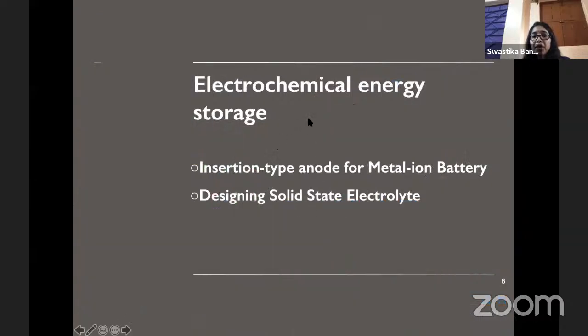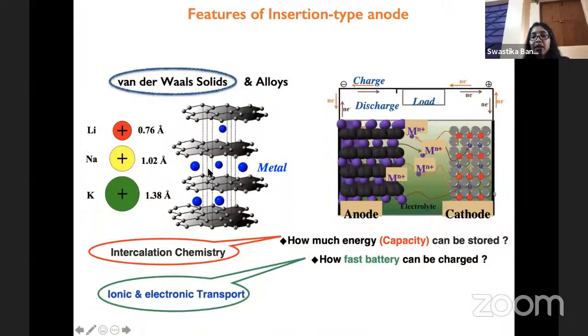However, for electrochemical energy storage, where we have problems with safety or energy density, we are going to deal with these two strategies. And the first one is the insertion type anode, as I was mentioning. So an insertion type anode is basically a van der Waals kind of material, and we can intercalate the respective metals. Like for lithium ion battery it is lithium, for sodium or potassium it's the respective elements. So we need to choose the layered system in such a way that it will allow the intercalation chemistry, which has very tricky criteria: how much energy can be stored depends on how many ions you can store, and how fast the battery can be charged depends on how fast these elements can be transported through the material, because when you charge or discharge, there is a shuttling process of the ions from the cathode to anode.